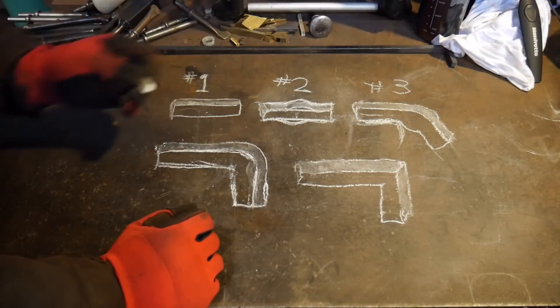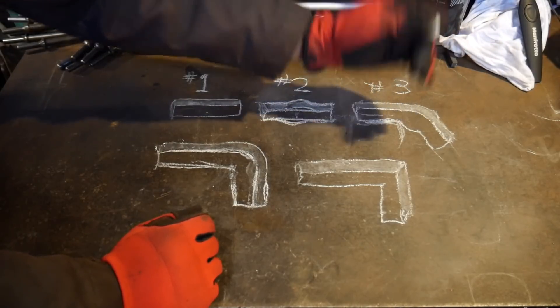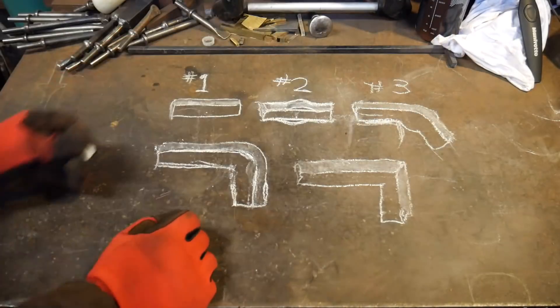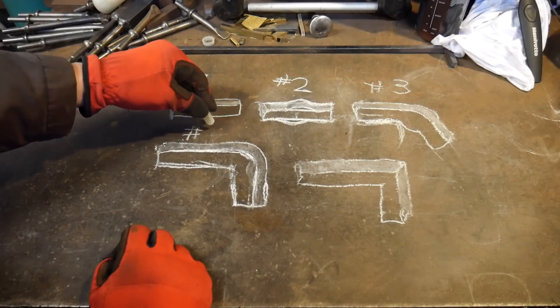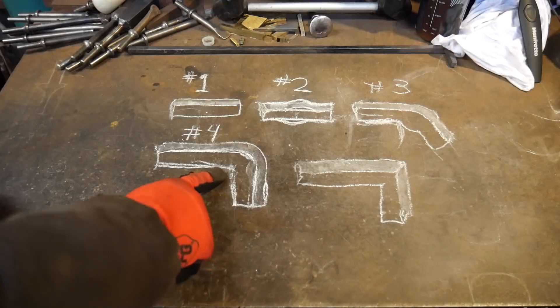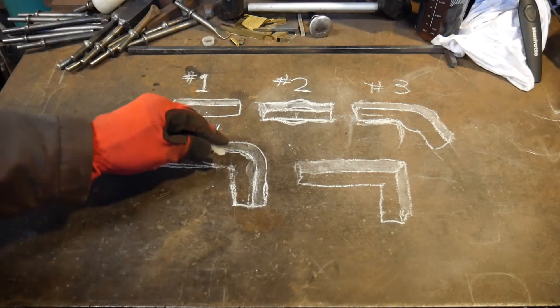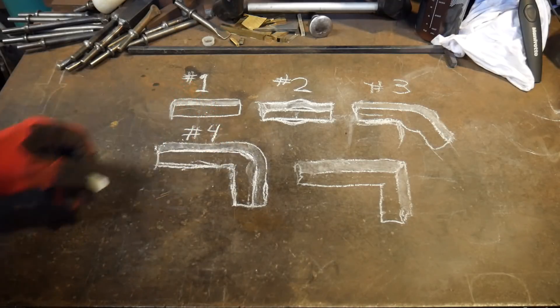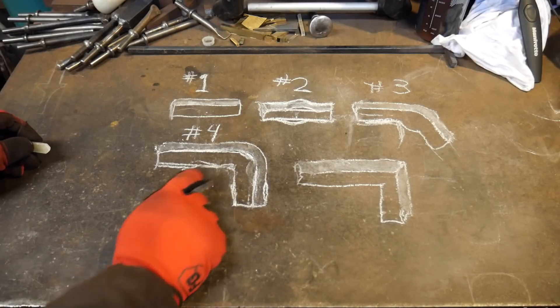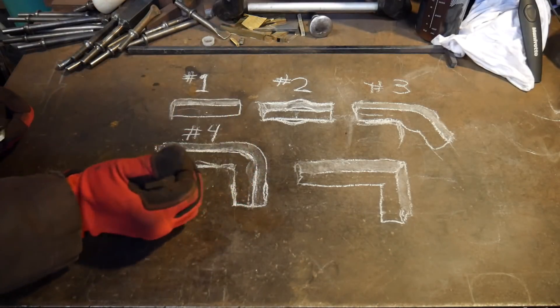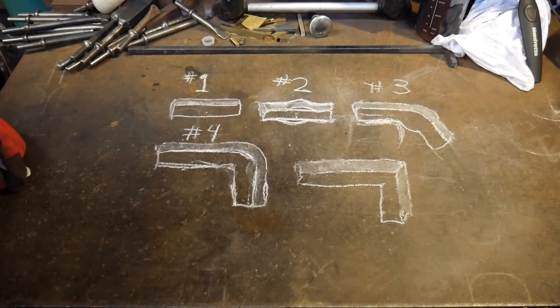That's the first stage. At this point, we don't want to create any sharp corners. We just want to get most of the mass bent into shape, into an L shape. And that's where number four will look like. You're just going to continue to dress that until you start looking like this. Now, we are going to begin to work the mass up against the corner, or whatever radius you want. If you want this more radius, put it on a larger radius edged anvil or block to keep a good radius on the inside of this while you work on getting that outside square corner going.